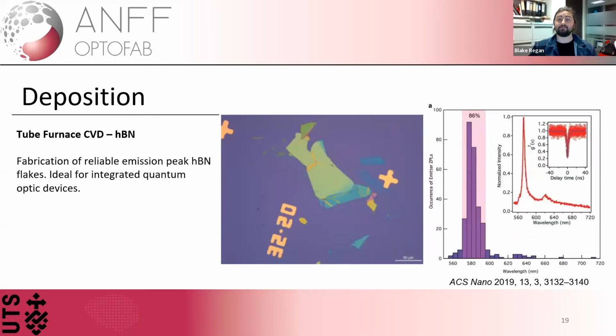In terms of our hBN, I included the figure from the paper of our PhD student Noah, which showed the nice thin emission spectrum, the 86% rate of always hitting near the 580 nanometer range of emission, and of course a g2 of less than 0.5, which, to those of you familiar with the photonics community, anything less than 0.5 is considered a single photon emitter. Now, the hBN samples are grown with these flakes en masse, so when we give you a sample, you're likely to have hundreds per sample rather than one or two.